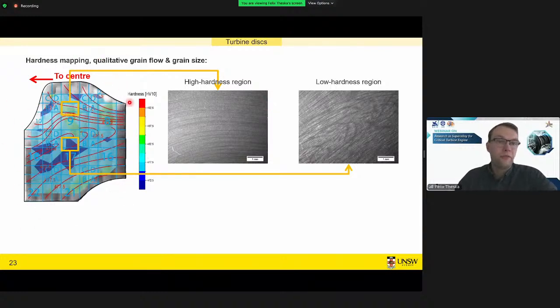It's a quite complex figure. The background is a macro etched image. The red lines, I just tried to redraw the grain flow for better visualization. And then on top of this, we see this color map, which is a hardness map, from blue to red, from low hardness to high hardness. If we just look at the macro etched images, we find there's some elongated grain flow in the high hardness region and this curved grain flow in the low hardness region.